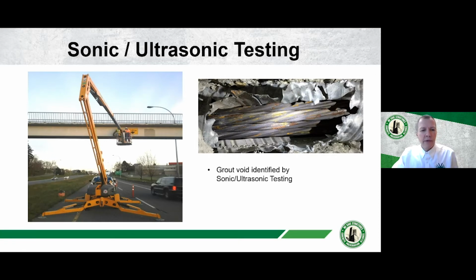Just an example of that, this is a picture of a bridge. It's a small bridge, a pedestrian bridge over a section of expressway out on the west coast. And the DOT was concerned. They had reviewed the construction records, and they thought that maybe they had some problems with the grouting on that post-tension pedestrian bridge. The people in the basket here are doing the same testing that you just saw in the video, and they identified a couple of areas where there were some big anomalies. Those areas were opened up, and you can see here that in this section there was no grout at all. And that was identified using the sonic ultrasonic testing technique and equipment.